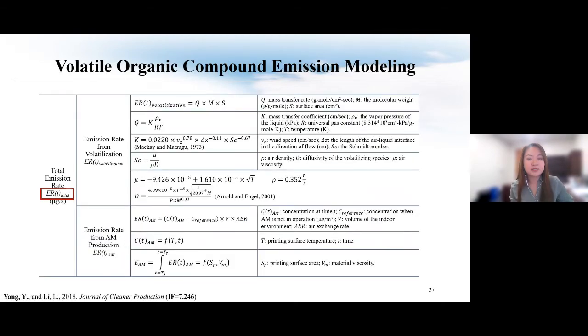Next, we looked at the VOC emission. What we did is we built the mathematical model. In this model, we have two emission sources. One is the emission because of the volatilization, meaning even when you don't 3D print, you just have that raw material sitting in your lab, VOC will escape from that material. The second part is VOC actually caused by 3D printing. For example, during printing, the build platform moves in and out of the material tank. That disturbance will facilitate the process of volatilization. Also, during printing, the temperature is going to increase, and that can cause additional emission as well.